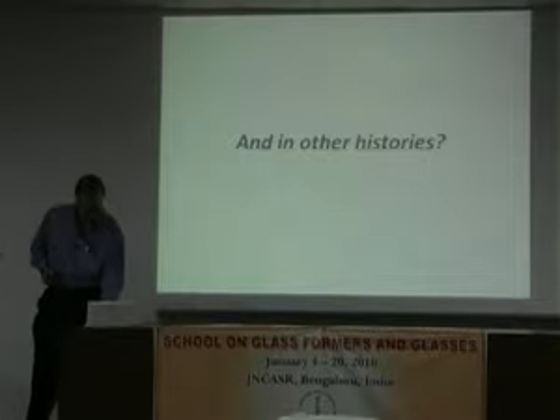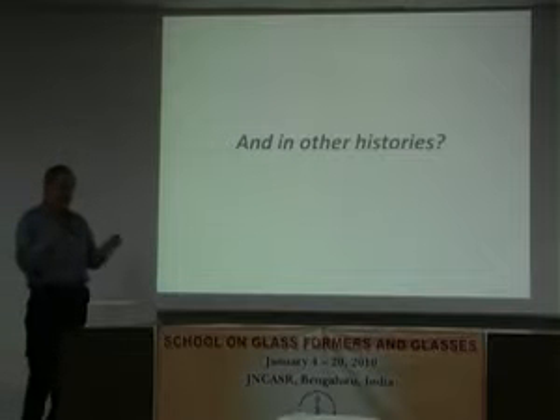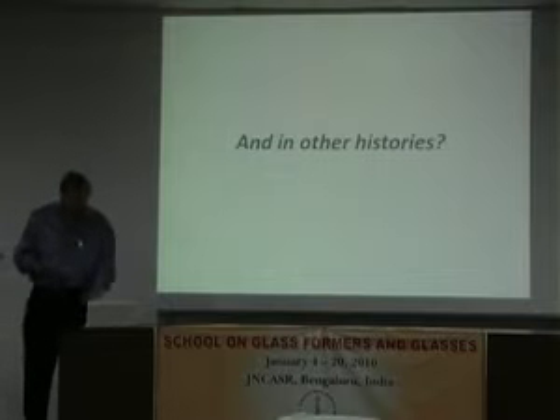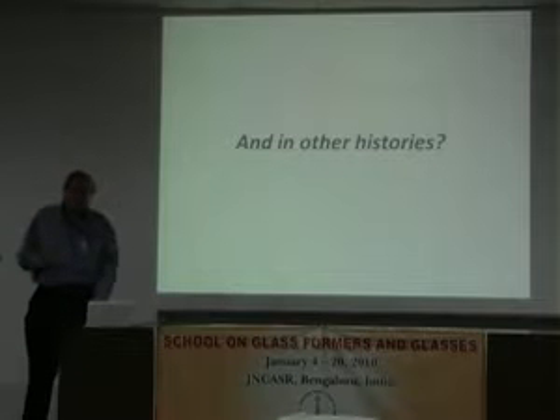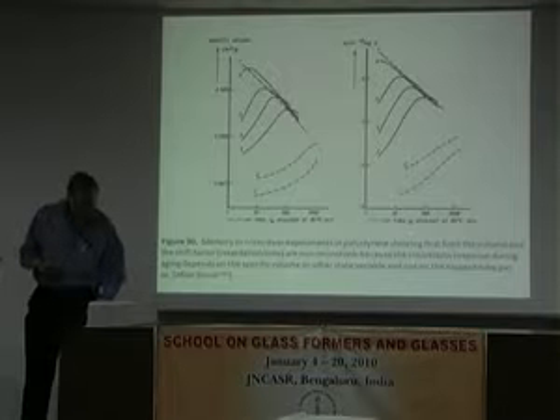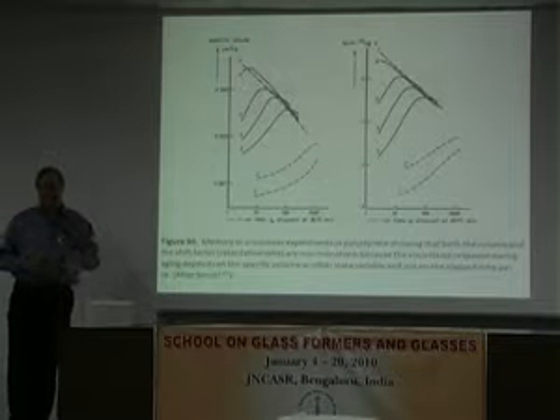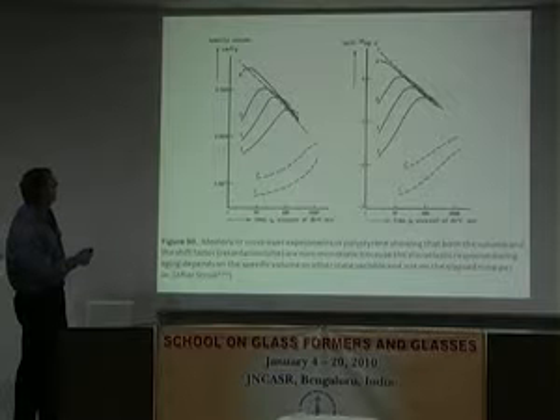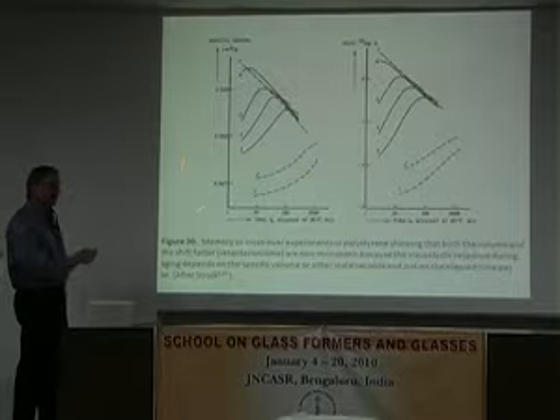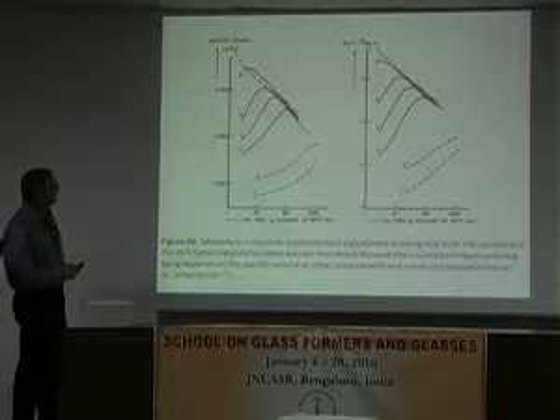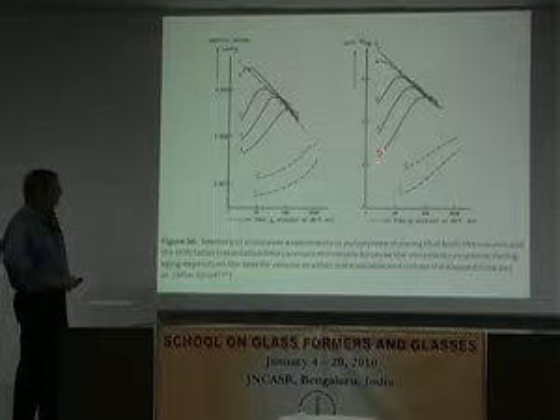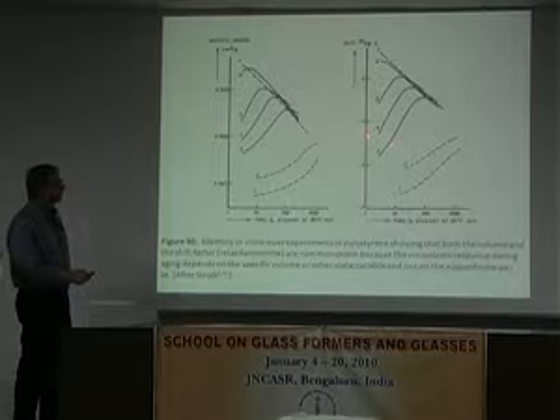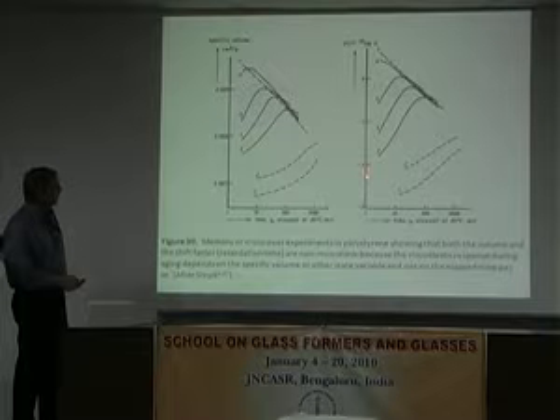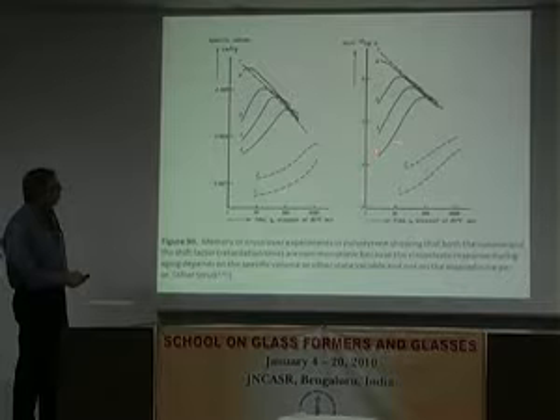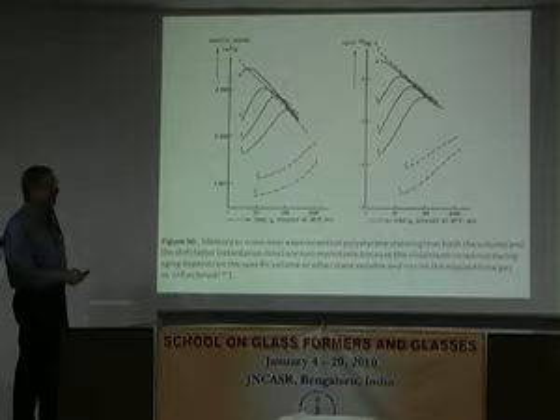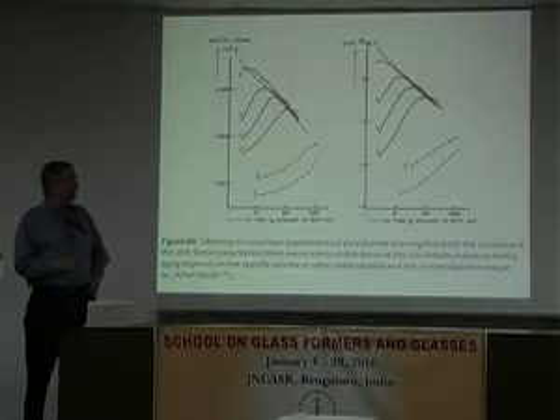Now, how about other histories? This is really the key to understanding this. Does it really depend on the structure of the glass? And so Struik actually did a series of experiments. He did asymmetries. He did memory. And this just shows the memory where he's showing the specific volume, just like I showed you yesterday in those two-step temperature jumps. And here he's showing the shift factor, which is going to be the negative of the log of the relaxation time in this case. And as the volume goes up, qualitatively so does the mechanical relaxation time. Okay, so that's actually very nice.